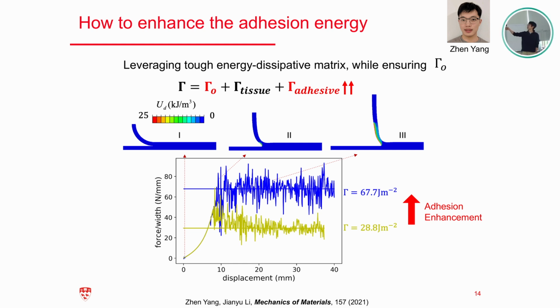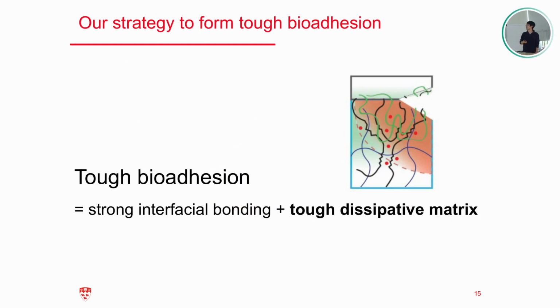For example, in the simulation, we can engineer or tune the model for this adhesive matrix, and when we make it tougher and easier to dissipate energy, you can appreciate that the overall adhesion energy gets much higher, right, compared to the case where you have a brittle matrix. So here we can achieve a significant overall adhesion enhancement by tuning up the contribution of the third term, the adhesive matrix. So that points out the direction for our design, right?